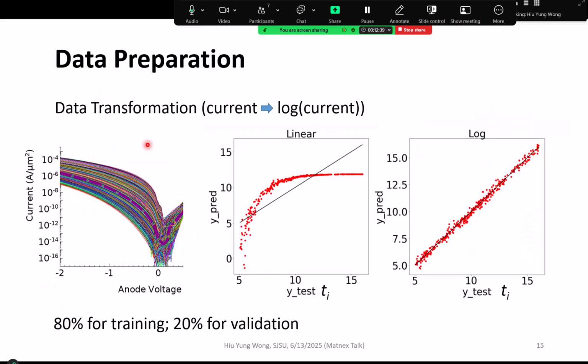And definitely, you all know that it is very important to determine if we need to do some data preparation. For example, in this case, we need to do some transformation because what I'm showing here is the log scale, right? So you can always think about this like a kid, a kindergartner. You tell the kindergartner, okay, for that thickness, you get this curve. For this thickness, you get this curve. Now I get this curve. What is the thickness? If you put it in the linear scale, this is basically 0. The kid will say, well, any of them, because they're all 0. But if you want to distinguish, you need to put it in log scale. So here we show that if you pre-process it to log scale first before you do the training, the prediction is much better than with the linear scale.